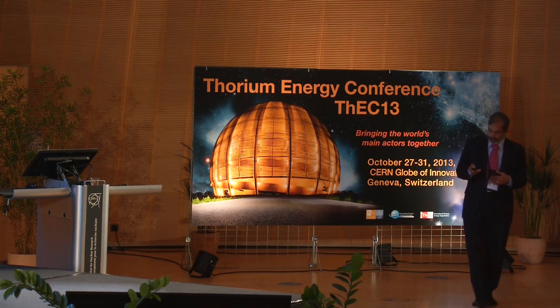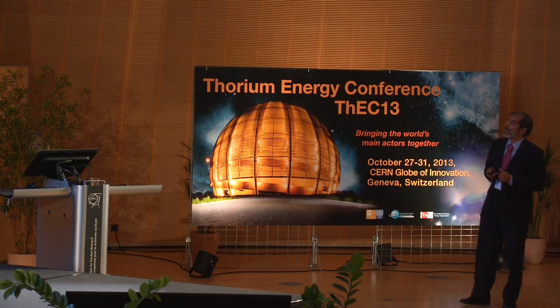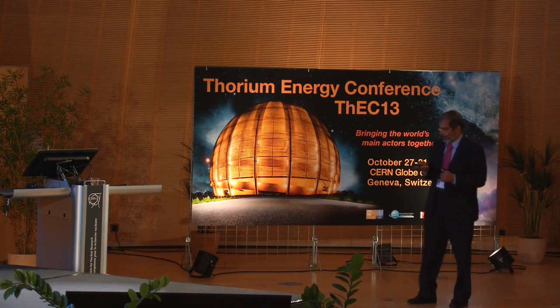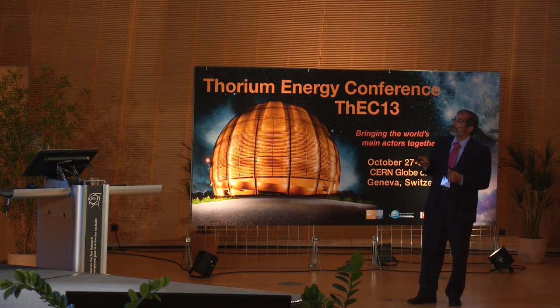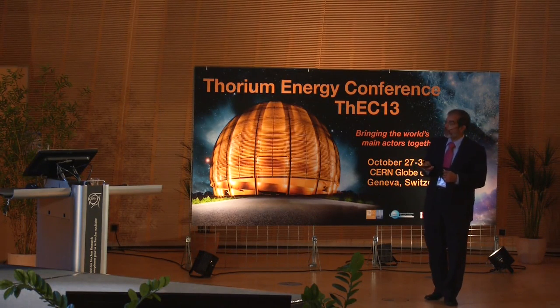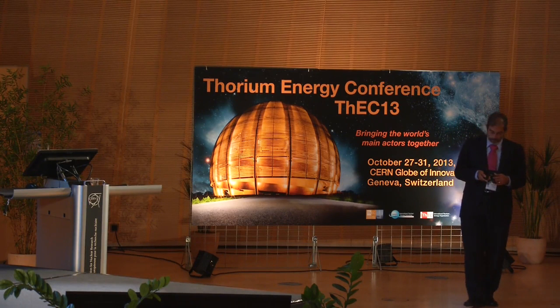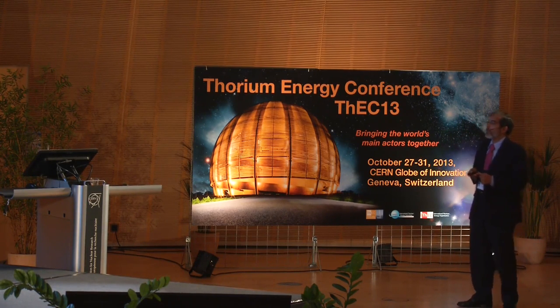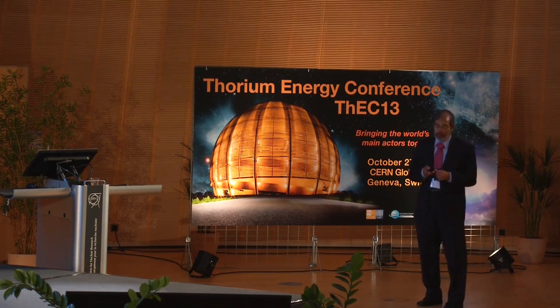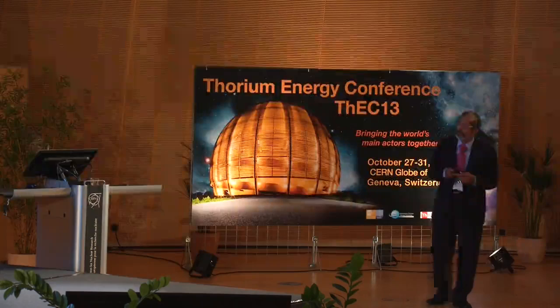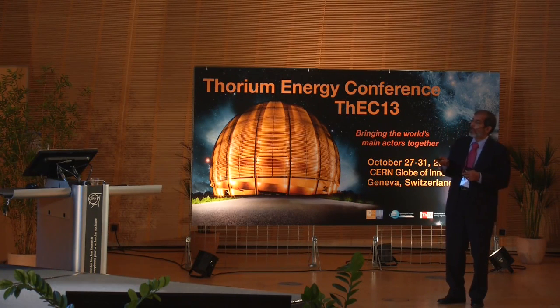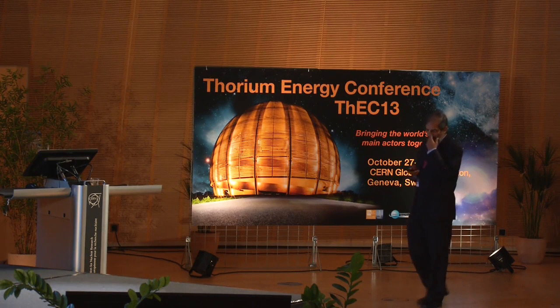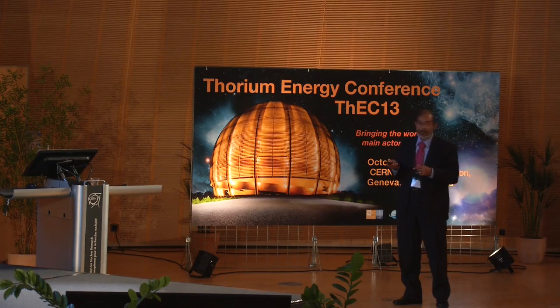Well, again, this has already been mentioned. It has intrinsic proliferation resistance because of the high energy gamma emitted by one of the intermediate products that form because of the n,2n reaction. This has also been talked about. Thorium has a greater energy advantage, especially if you are going for very high burn-up. And by virtue of being lower in the periodic table than uranium, it produces fewer minor actinides.